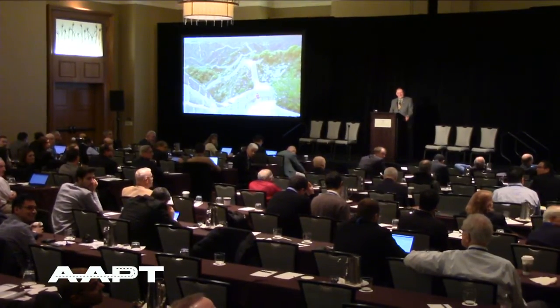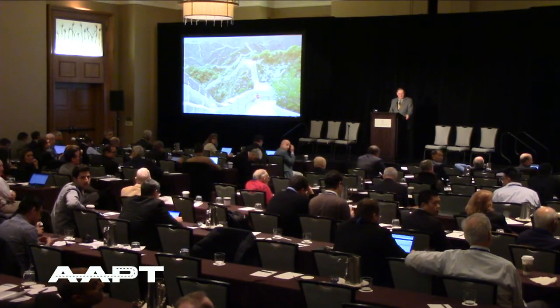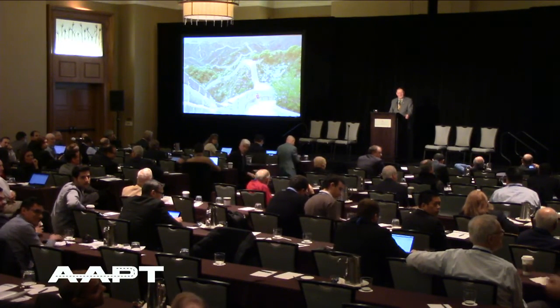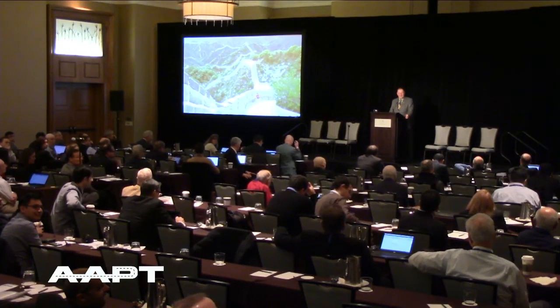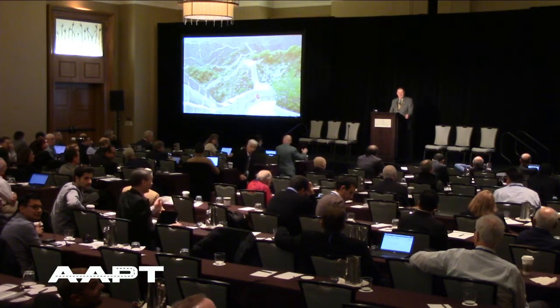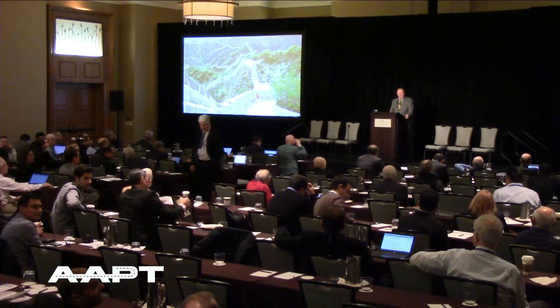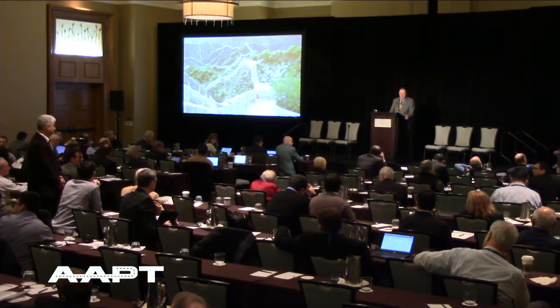So one of our big concerns, of course, were these extremely heavy loads, what Jerry was showing there. And what we found, of course, is if you put 20 inches of hot mix over a strain gauge, it'll do pretty good. The 6-inch section where you've got a strain gauge underneath those kind of loadings, you didn't have any pictures of it, but I know you've been back to visit that particular section, S5, and maybe you could describe what it looks like, but there's a tremendous amount of deformation. I'm not sure the gauges are working there anymore, but that section experienced a tremendous amount of bending and a lot of deformation. Yeah, and of course those gauges were only 6 inches from the surface because the HMA thickness was only 6 inches. All right, great. I hope most of the strain gauges basically survived the entire testing. I would assume so. Thank you.